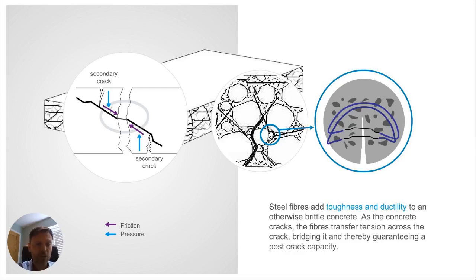The idea of having 3-dimensional reinforcement is that when concrete exhibits an initial yield, there will be fibres inside that concrete mix. And the idea is that they will bridge a crack and transfer stresses from one side to the other. Now you can imagine these steel fibres, depending on the fibre type or the dosage, they usually count for around 100,000 fibres per cubic metre, and sometimes more. The idea being that there will be such a network of reinforcement in there that when there is this initial yield, there will be reinforcement in the locality to do so.